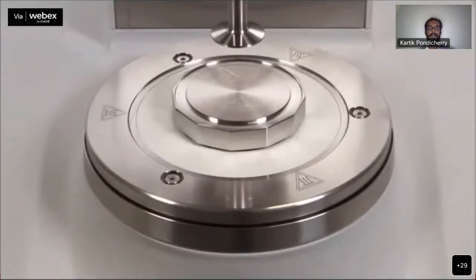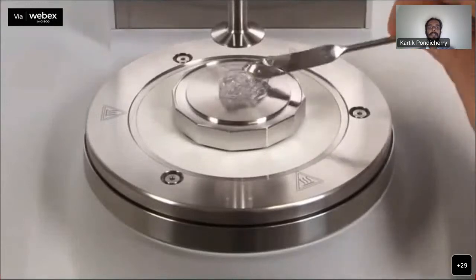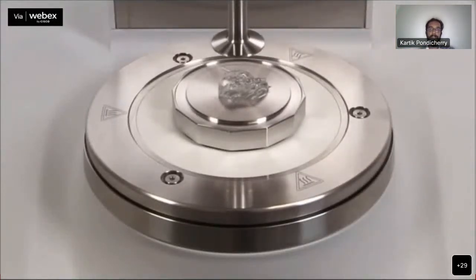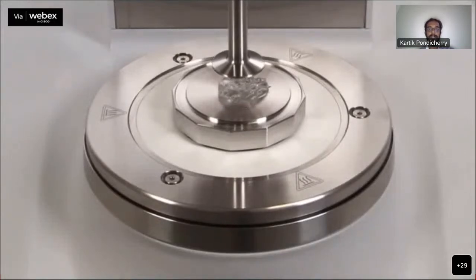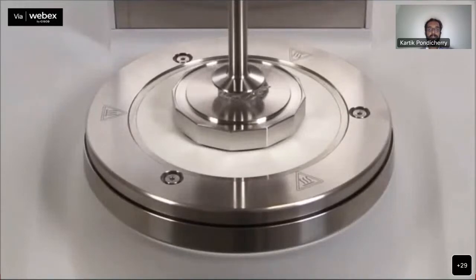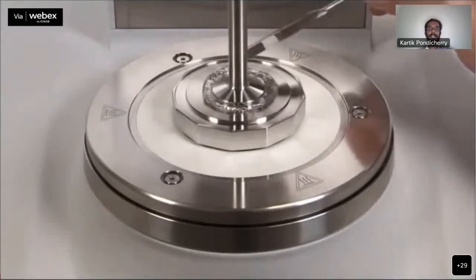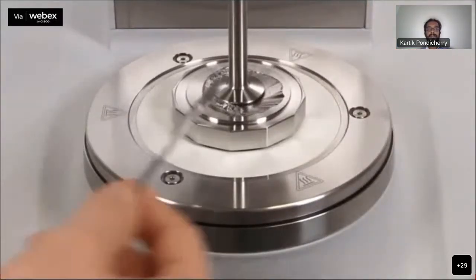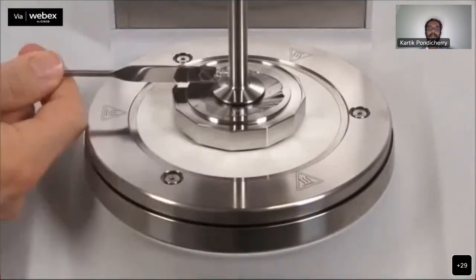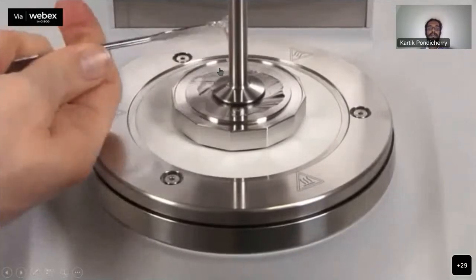Different measuring setups. This is a very short example of how you actually do this measurement. It's a typical setup, a plate-plate geometry, like you saw this parallel plate or two-plate geometry. The bottom plate, the top plate, and then the sample in between. This is an accelerated video, so it's going a little faster than it's supposed to in real life. Because if it goes this fast, then it's going to give some kind of shock to the sample, which is not desired. So you trim away the excess. And then the point here being, you know the exact area of this particular upper plate. Then you know exactly the surface area. And then you know exactly how much height the sample is. And then the force that you apply, you apply so much force that you know that. And then you can measure the displacement and at the end of it, you get all the parameters that you need to calculate viscosity or viscoelasticity.